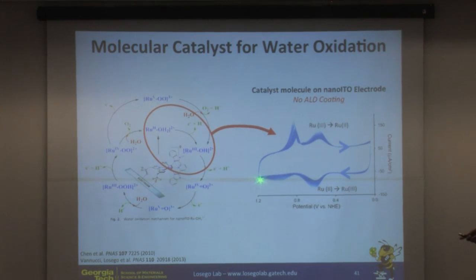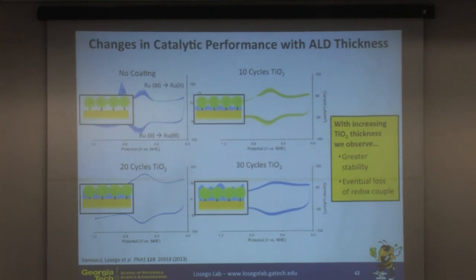But what we can see when we do cyclic voltammetry, we can see this redox couple related to this process here, and that indicates that we're getting catalytic activity. Now, if we run this cyclic voltammetry multiple times, we start to see a reduction in the redox currents, indicating that these molecules are coming off of the surface and they're detaching. So this loss in current is indicative of degradation of the device. Okay, so increasing number of cycles, loss of catalytic molecules.